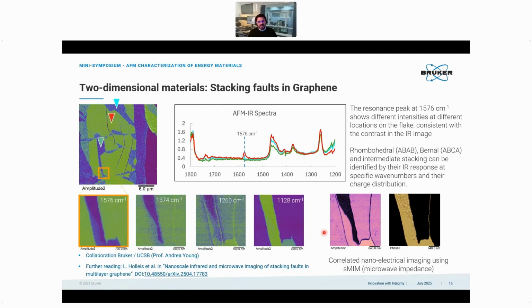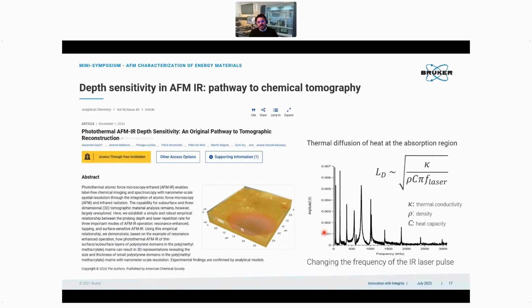And finally, I will end with this result, which I personally find extremely interesting, because I've been working on something similar, but more on the electrostatic side, electric properties. This is a first result on the pathway towards tomographic imaging of nanochemical mapping, right? The result here is also published by Alexander Dazzi's group in collaboration with Bruker. Here you see a 3D reconstruction of a sample where the reconstruction is chemical mapping. So you get images at different depths of the chemical contrast, and then you can reconstruct a 3D tomographic image of that. Now, you might wonder, and I will put that as simplified as possible, but we'll be happy to answer your questions about it, how could we do that?